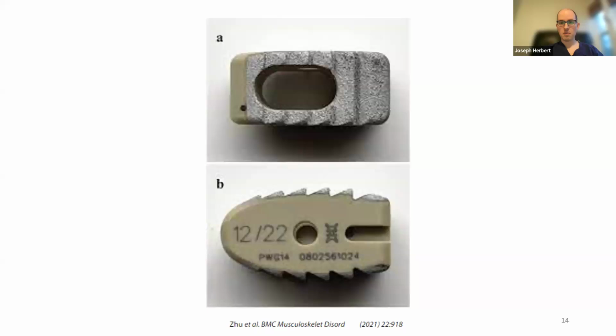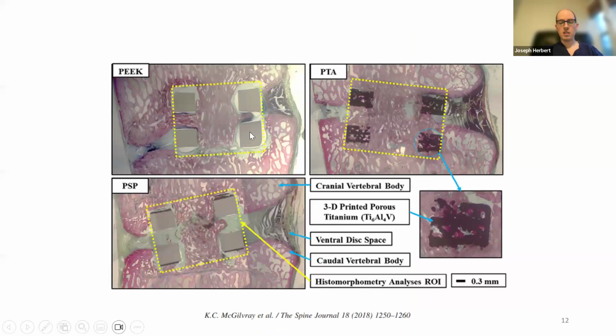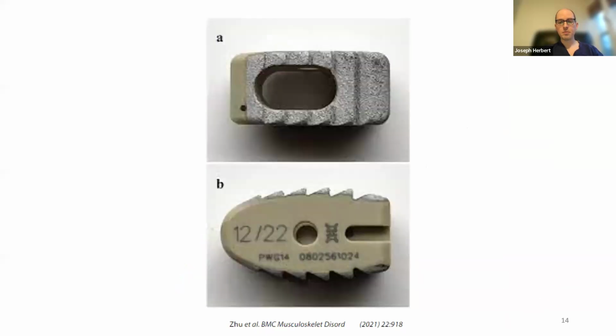And probably the residents have seen implants like this used at some point or another. But this is, again, a PEEK cage, which is very biologically inert. If we go back to here, you don't see any bony ongrowth, not just ingrowth, which you have here, but the bone actually doesn't. It's almost like the bone doesn't really like the PEEK. It kind of stays away from it a little bit. Whereas this surface is a combination of titanium and hydroxyapatite, very rough texture, and this helps bony ongrowth. So this is another example of using inorganic compounds to induce biological activity.